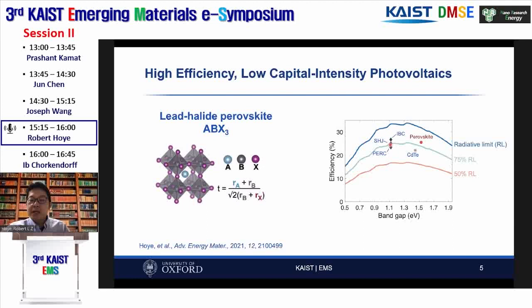So if you look at silicon, this has been developed for over four decades now, and it's now settled at efficiencies around the 75% of the radiative limit line. And contrast that with the perovskites: these have only been developed for just over one decade, and yet they've already crossed this threshold, and the best perovskite devices are now approaching the best efficiencies of single crystalline silicon PV.